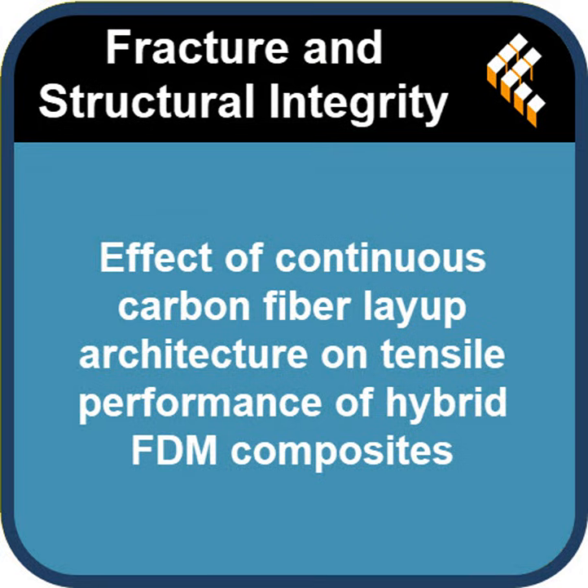How do they combine them without compromising the overall strength? They designed what the paper calls a quasi-laminate architecture. They tested a specific combination, layering fibers at 30 degrees, then 0 degrees, then negative 30 degrees. Putting that 0-degree load-bearing fiber right in the dead center. Yeah, sandwiching it between the angled fibers, you get a central spine for raw strength wrapped in a crack-resistant skin. Here's where it gets really interesting, though.